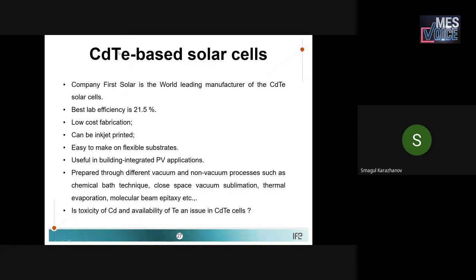The challenge is related to availability of tellurium. Tellurium is one of the strategic elements in the Earth. And of course, cadmium is poison, but this poisoning property will be available only during material synthesis, probably. But during utilization, no, because for this poisoning property, cadmium should be released, but cadmium release will be at temperatures exceeding 1000 degrees C, whereas these types of solar cells will be utilized in terrestrial conditions at room temperature.